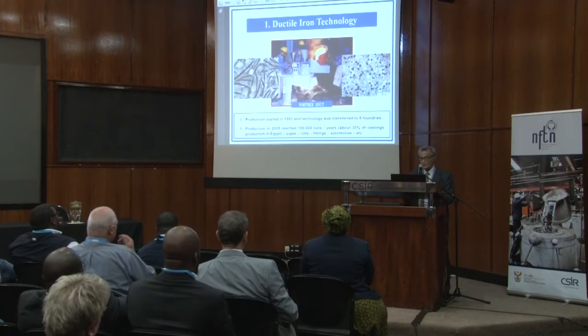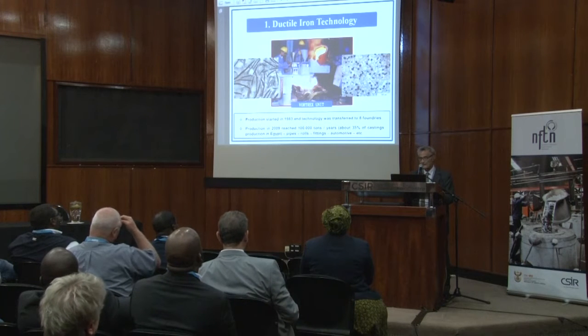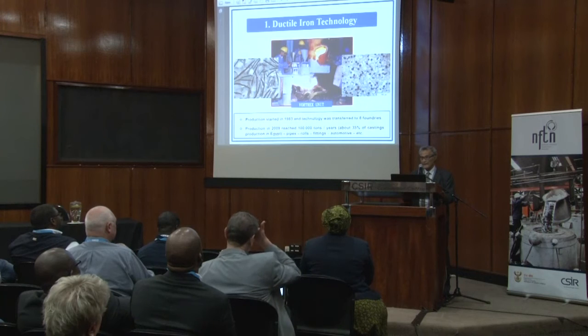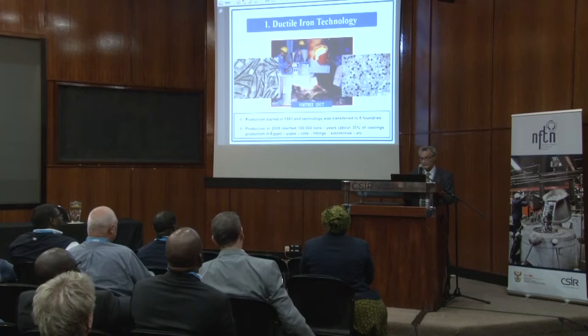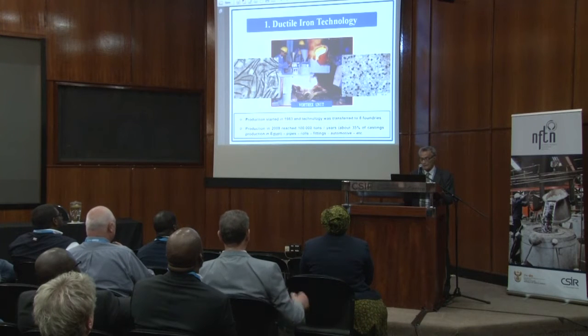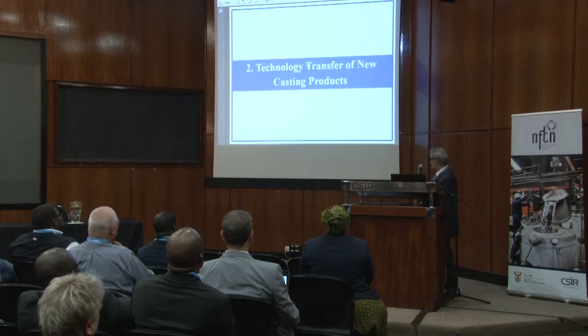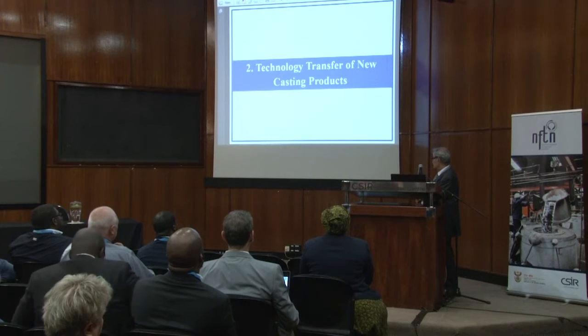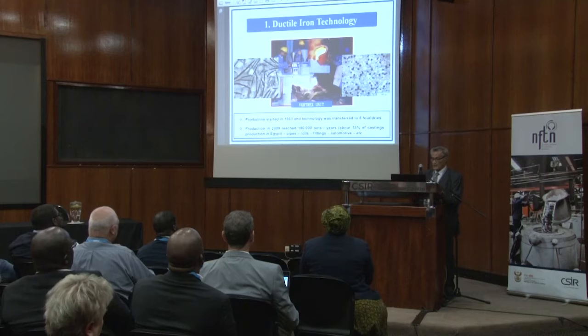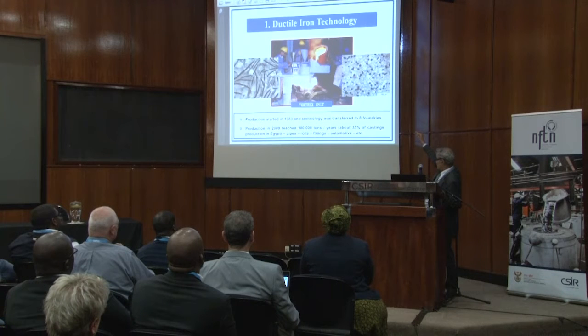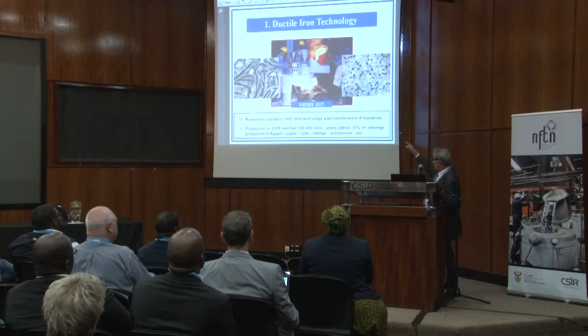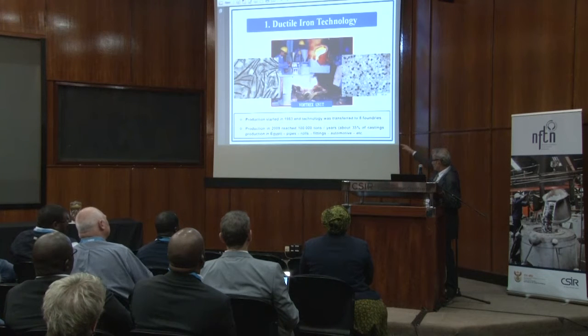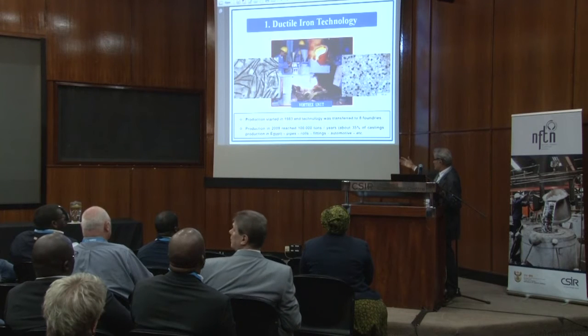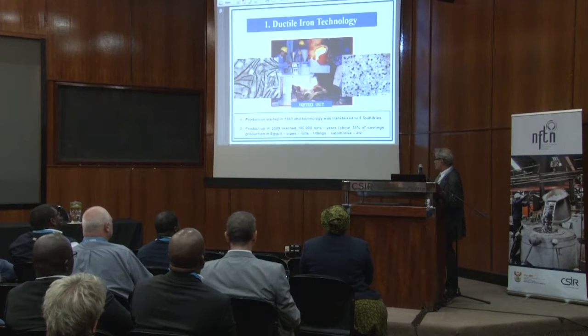We developed this technology because addition of magnesium is not very easy. It is a very pyro process and sometimes gives explosions and some dangerous effects. We developed this very safe technology, which we call the vortex process, where we pour the molten metal in this tundish, and the metal goes to this compartment tangentially. It rotates in a vortex, and then we add the magnesium alloy through this hopper in the middle of the vortex. And then the reaction is very mild. As you see, people are standing beside it with no danger at all.